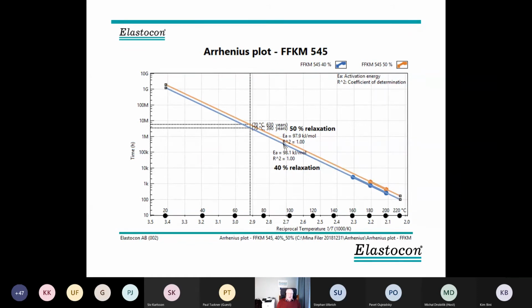This is plotted in software we have made in our company, because we found it impossible to make a graph in Excel which shows what we want to show. For example, here we have 1 over absolute temperature in Kelvin. But these figures don't tell you very much. So we put in another axis with the Celsius temperatures, and that is not linear and not logarithmic either. But now at least we know where we are.